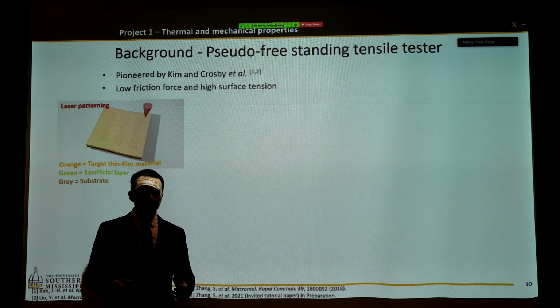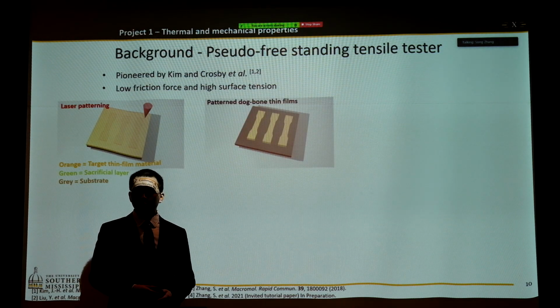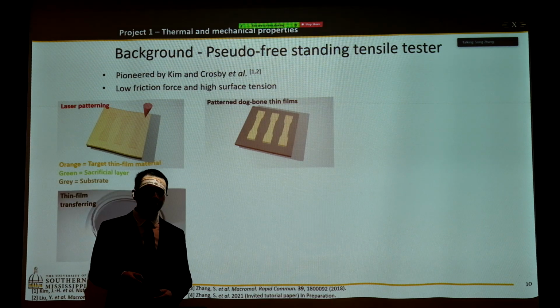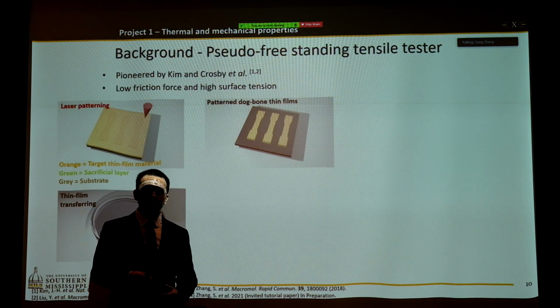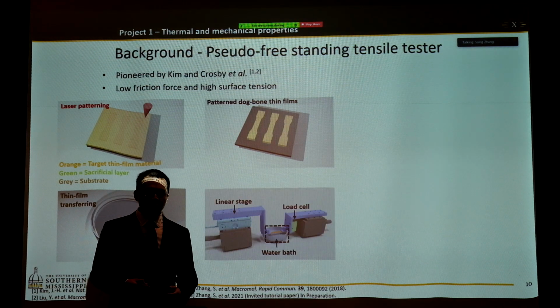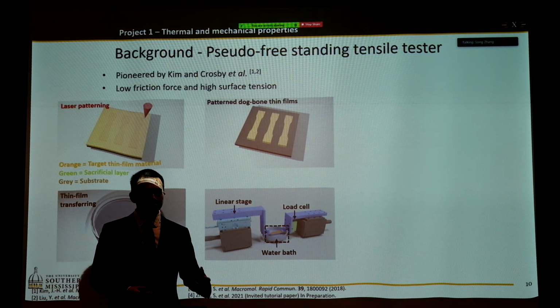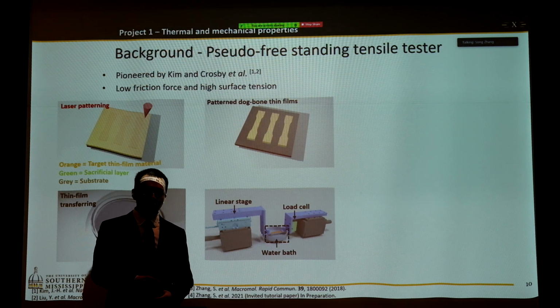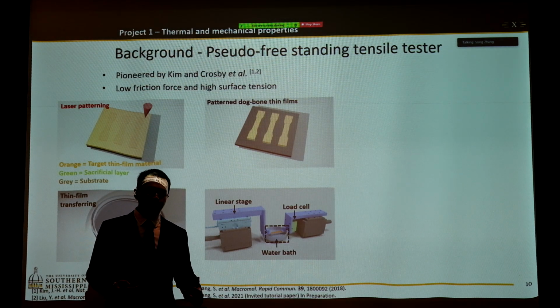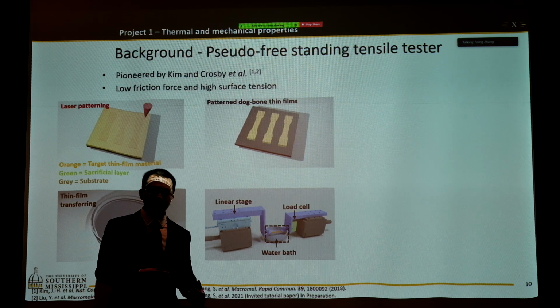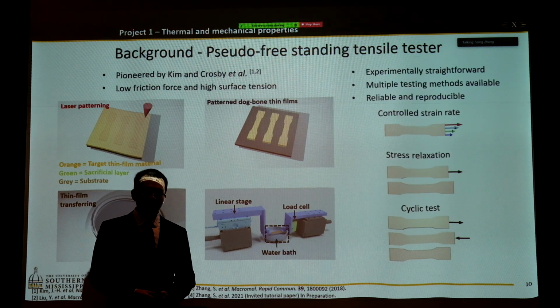Now, by laser patterning, we can pattern the dog bone geometry, and upon dipping the dog bone geometry thin film into water, the water-soluble layer dissolves, and our polymer becomes freestanding. With that, we connect one linear stage and a load cell on the two sides. We can get a real-time force-displacement curve, which can later be transferred into a stress-strain curve. And when compared with a bulk tensile tester, they're actually very similar. We have very high quality data.